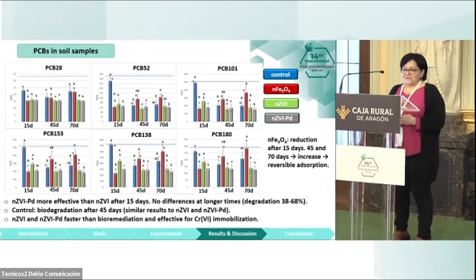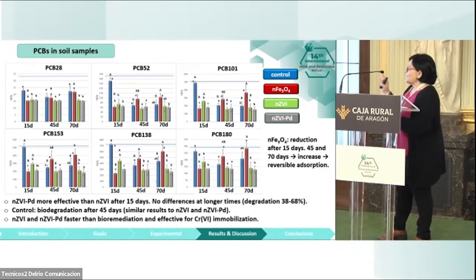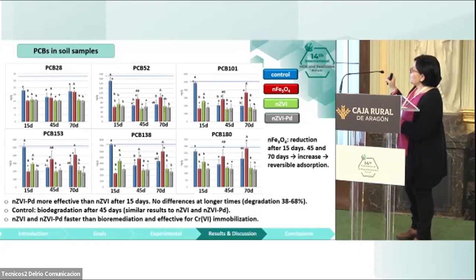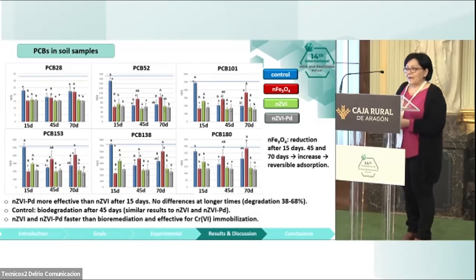And now we will talk about the PCBs. We analyzed different PCBs, and there are several graphs, but in the different colors we can see that both zero-valent iron particles, with palladium and without palladium, had the best result over time for most of the tests. Of course, we can see that in some of them there was a greater efficiency. And something quite surprising is that if we take a look at the red columns, this is nanomagnetite. So we can see that in the beginning the concentration of PCBs is reduced when we apply the magnetite, but then this increases. So this is a reversible process. According to some studies, nanomagnetite is used as something to extract the organic component. So in this case, it retains, but then it releases later on. So this wouldn't be an appropriate mechanism.